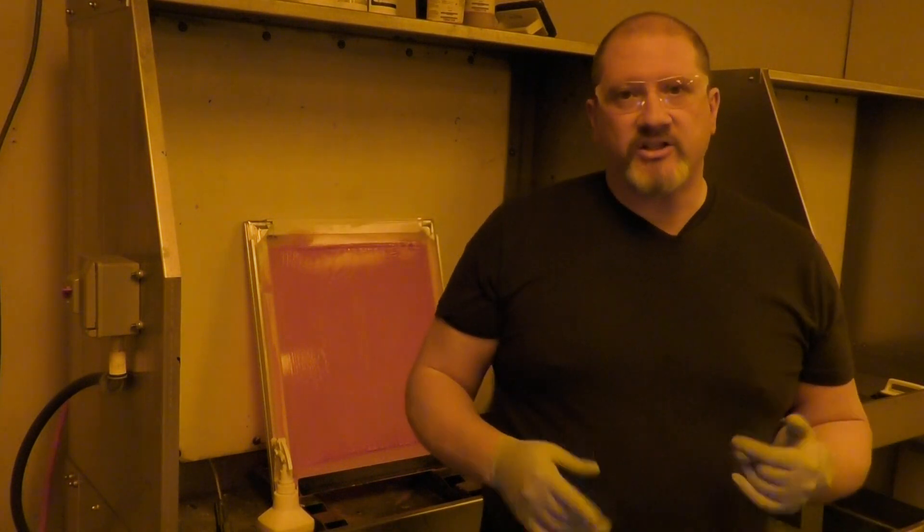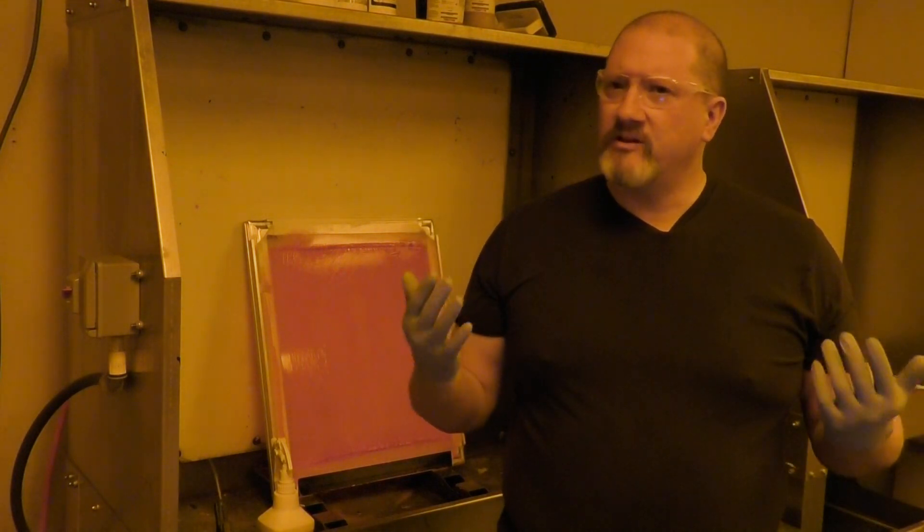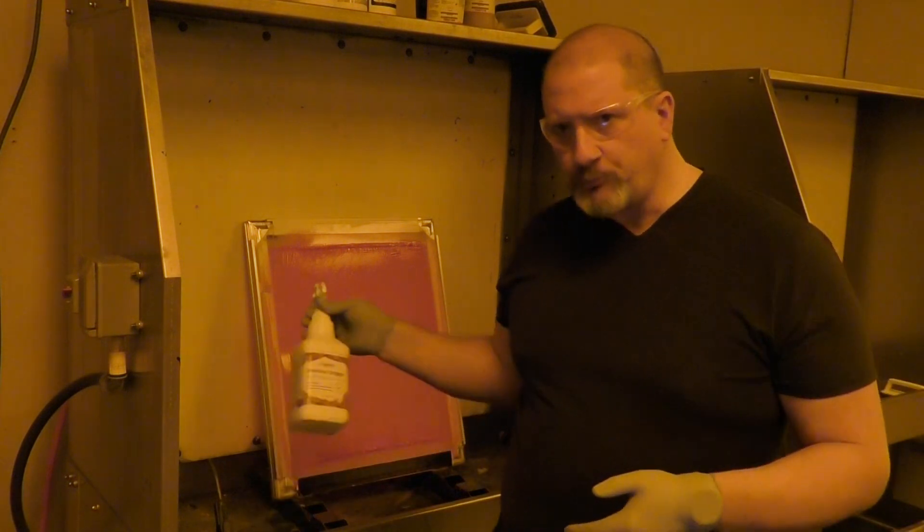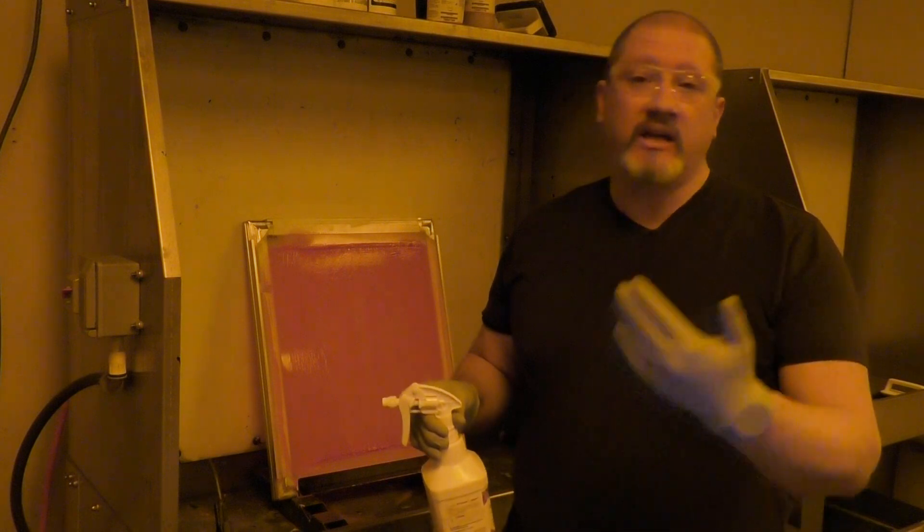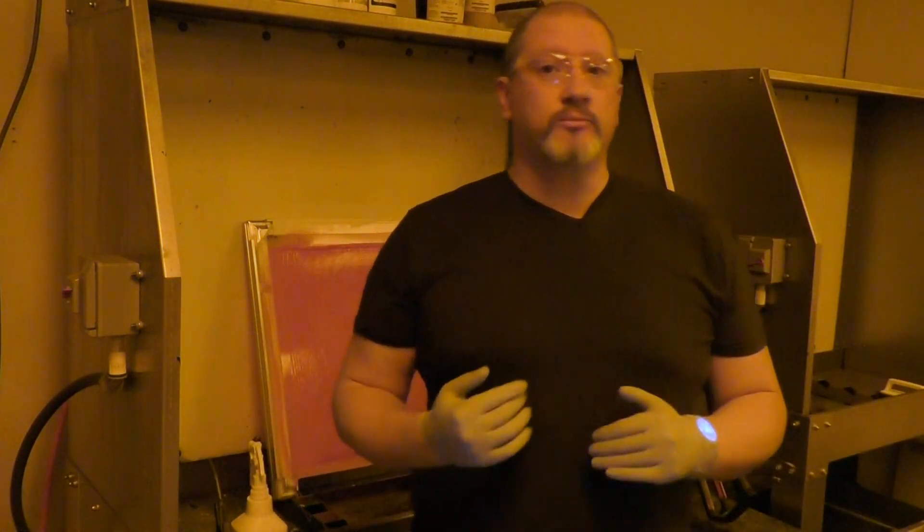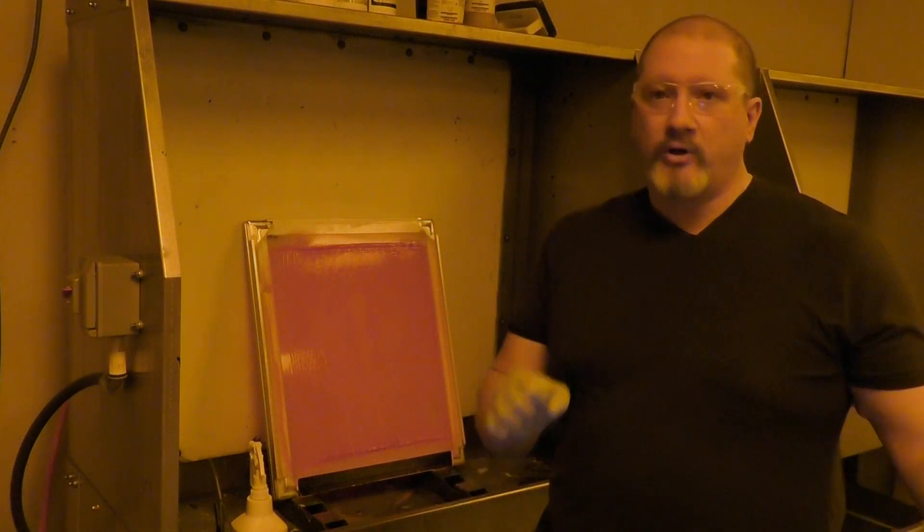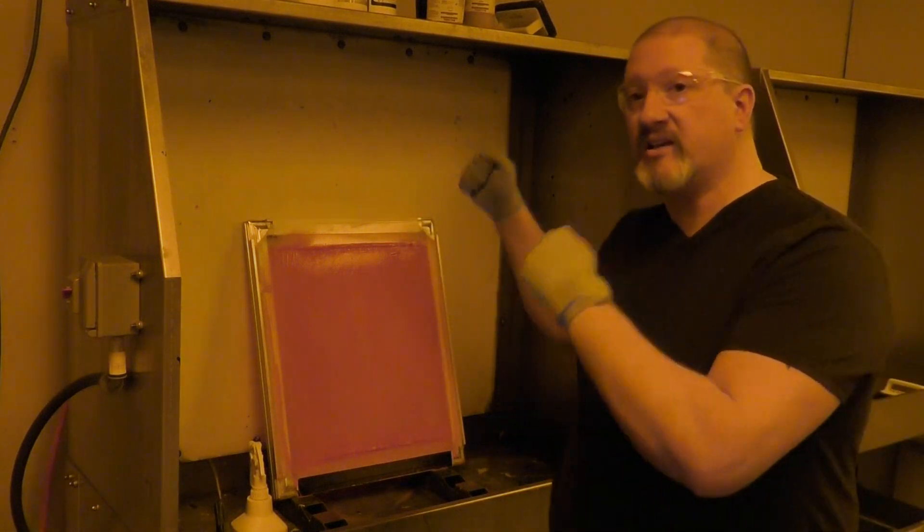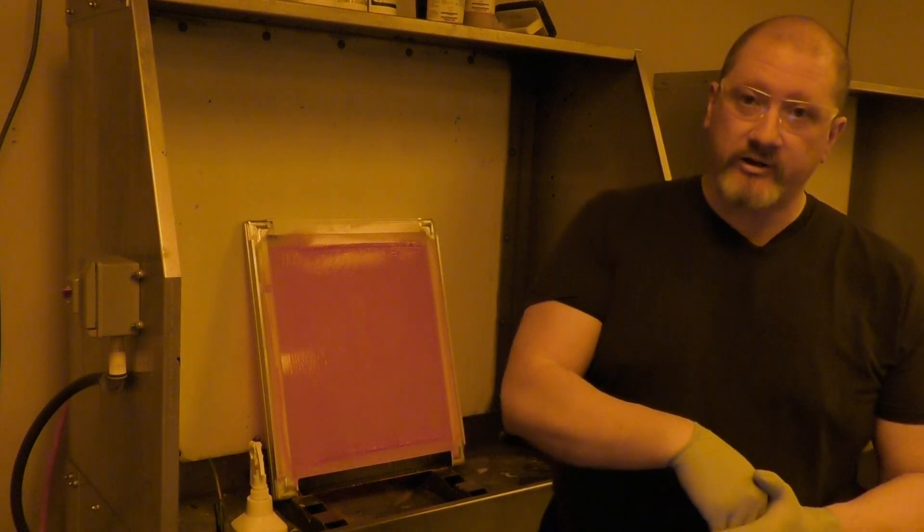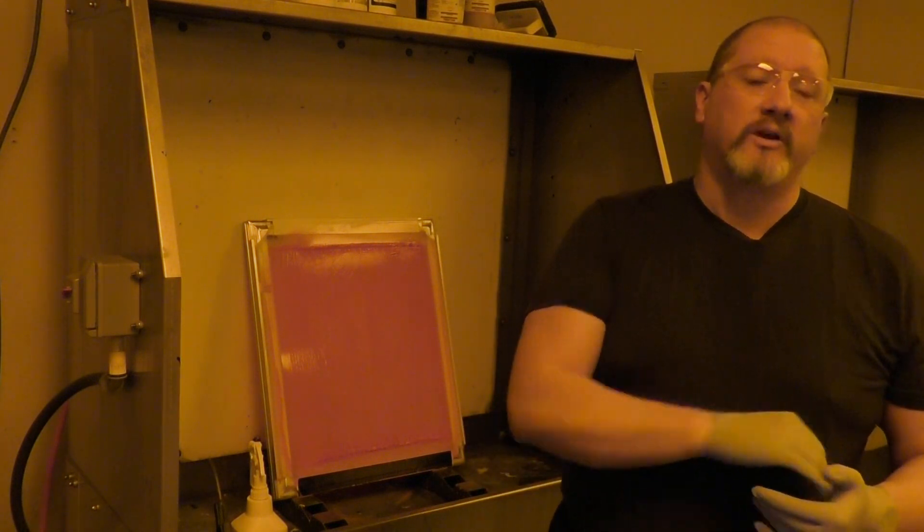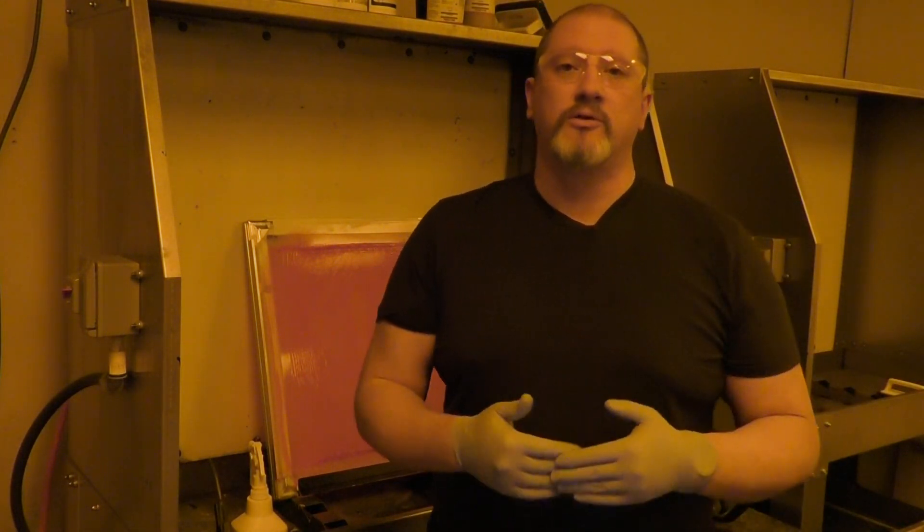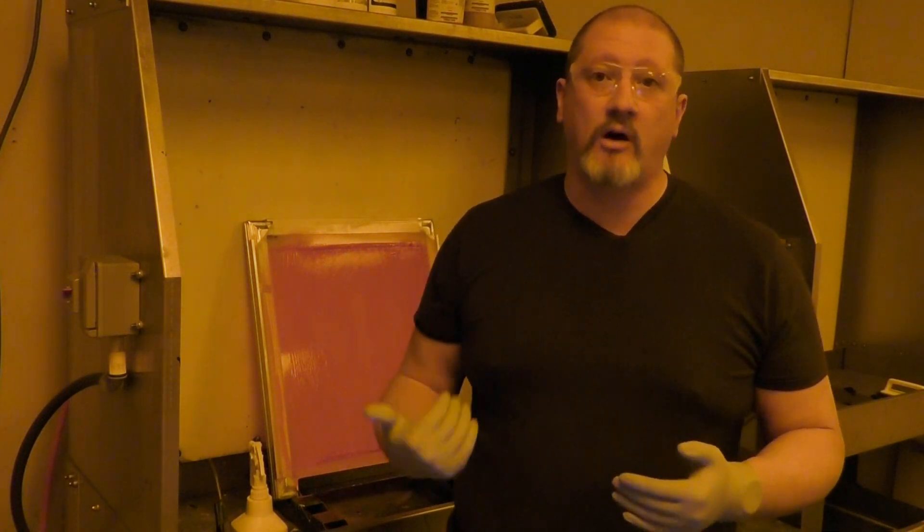So if you have that kind of issue and you look at the label, it's possible that you added too much water to it and it's just not as strong. If you're using a dip tank, it is much more possible that through the act of putting screens in and taking them out, and when you're taking out, you're taking out fluid from the tank as well that's clung to the screen. Over time we have to add water to it. Most often we're not refreshing with any stencil remover, so we've actually started to lose stencil remover in there. The percentage is too low, and we just need to refresh that.